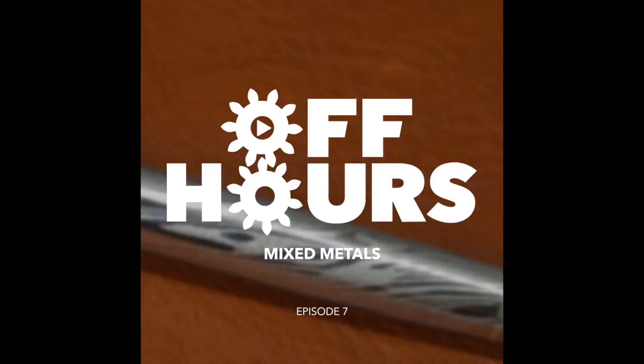No, and in fact, that's beyond really what I'm able to do easily. You can certainly pull, especially if you're dealing with gold or silver, you can pull those out of another metal quite easily. There's various acids and things like that you can dissolve gold or silver into, and then you can take that solution and precipitate out the gold or the silver. But at a small, shop scale, that's not really practical. So at that point, if you've screwed up a billet of material, you're sending it back to your refiner and having them do it. But of course, the problem there is that you're paying for them to separate out those metals and recover them. So you might only get, let's say, 80% of the value of the precious metals back. So even if nothing goes right, yes, they can recover the metals, but you're not getting the value back. So what are some of the mistakes you've made or difficulties you've encountered experimenting with making mokumegane?